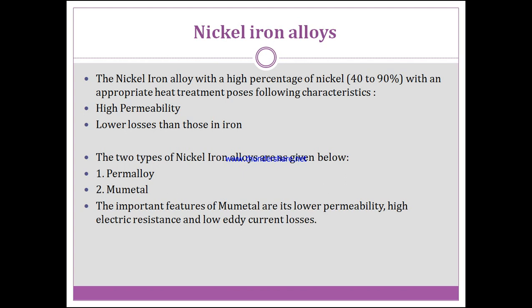Because of including the high percentage of nickel, that is 40 to 90% of nickel, added in the iron, we can get two important characteristics, that is the high permeability and the second one, lower losses. Now there are two types of nickel iron alloys given below. The first one is permalloy, and the second one is mumetal. The important features of mumetal are its lower permeability, high electric resistance, and low eddy current losses. According to the various proportions, we have made the two sub classifications, that is permalloy and mumetal.